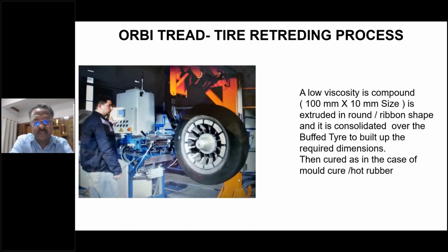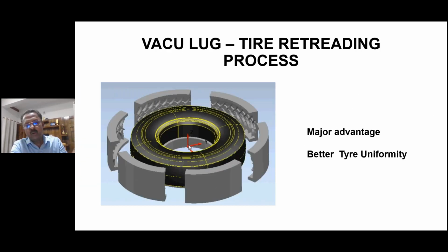Orbitread is mainly used for OTR tires, big tires, where a small strip is extruded and wound over the buffed tire casing to the required dimensions, and then it is cured similar to hot cure or hot rubber. Vacu Lug is similar to hot cure. The difference is that we use segmented molds, so you get better uniformity.